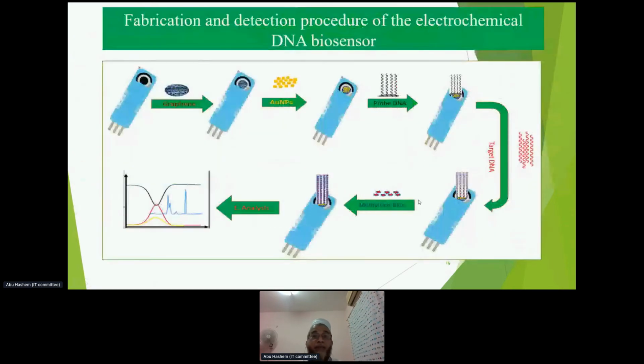This is the overview of our experiment. The fabrication and detection procedure of the electrochemical DNA biosensor is shown here. This is the SPC electrode. First, we fabricate it with graphene, followed by gold nanoparticles. Then we immobilize the probe DNA. Then we hybridize with target and non-target DNA. Hybrid DNA was intercalated with methylene blue. Based on the methylene blue redox activity, hybridization was analyzed through electrochemical methods. In this step, electrochemical conductivity was recorded.